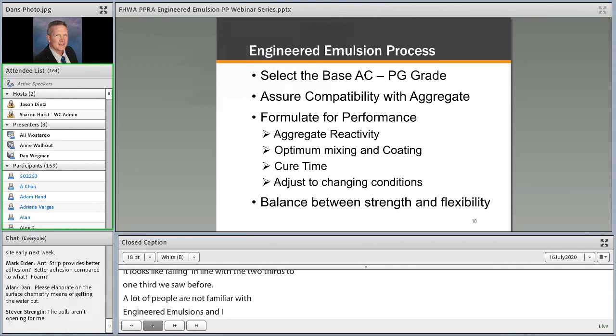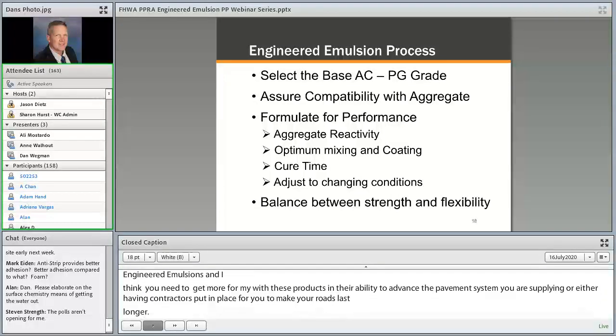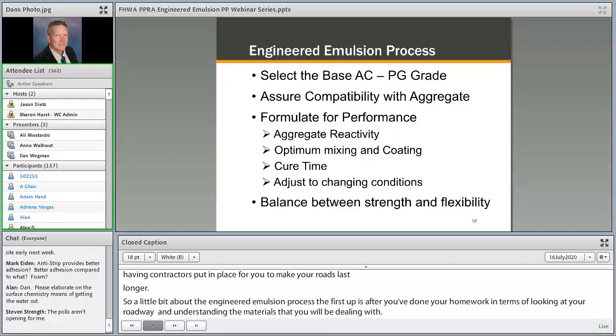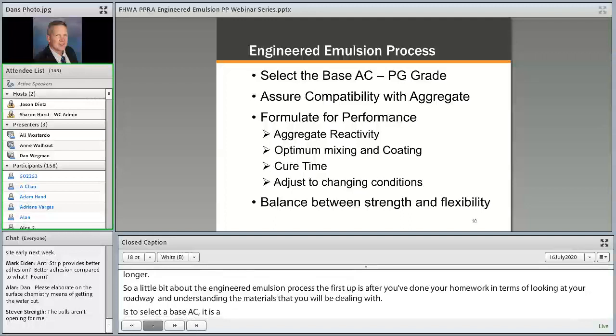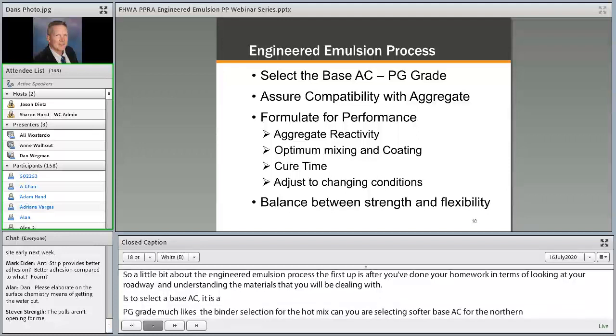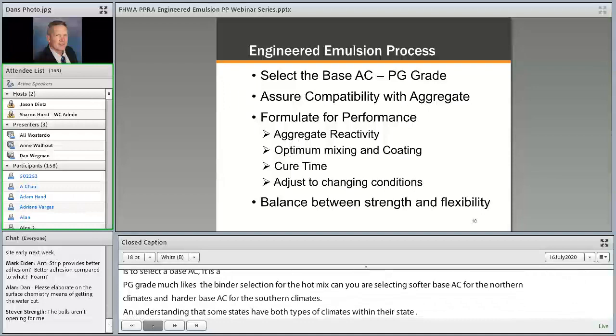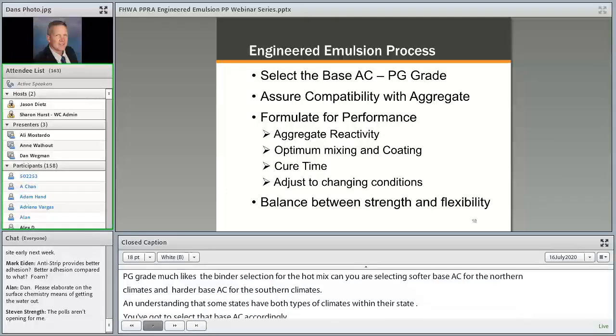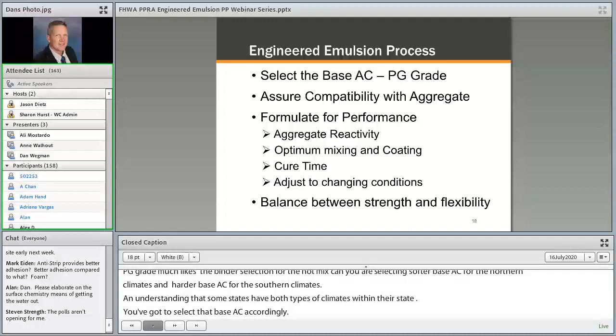So a little bit about the engineered emulsion process. The first step, after you've done your homework in terms of looking at your roadway and understanding the materials you're going to be dealing with, is to select a base AC. Basically you're selecting a PG grade, much like the binder selection process for hot mix. You'll be selecting softer base ACs for the northern climates and harder base ACs for the southern climates, understanding that some states have both types of climates within their state, and you've got to select that base AC accordingly. Keep in mind that in these applications, you also need to determine how far down in the pavement structure that material is going to be placed, because that affects your binder selection grade as well.